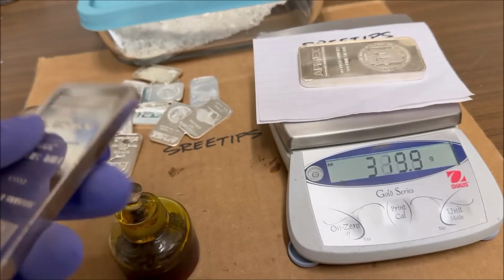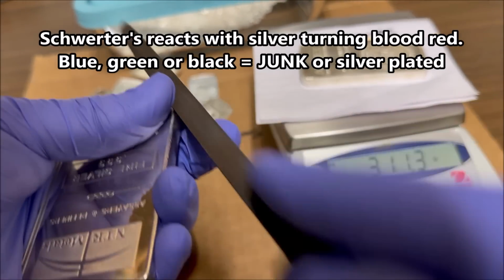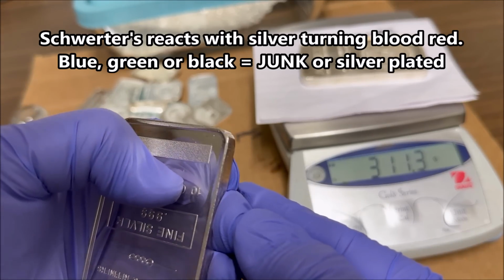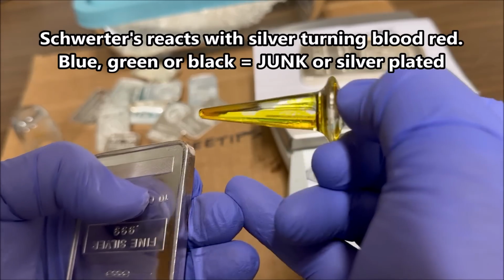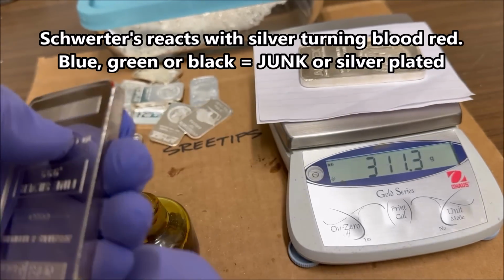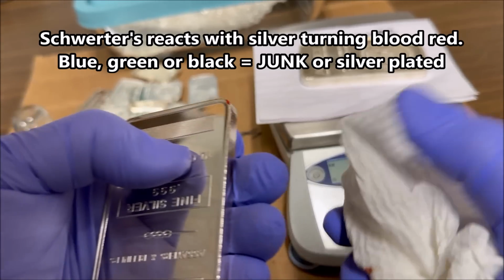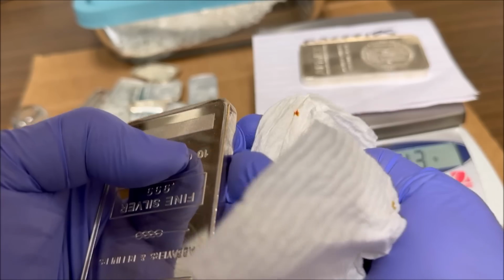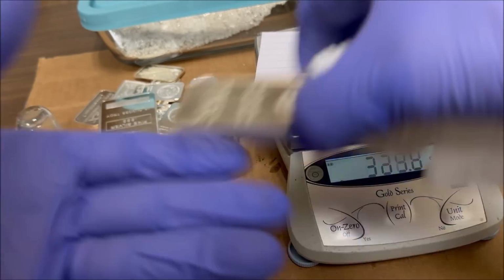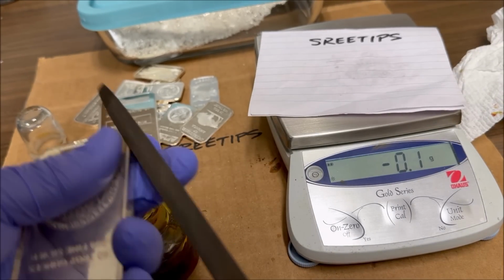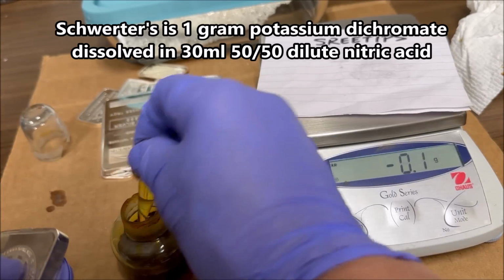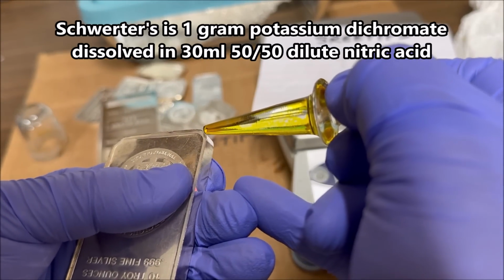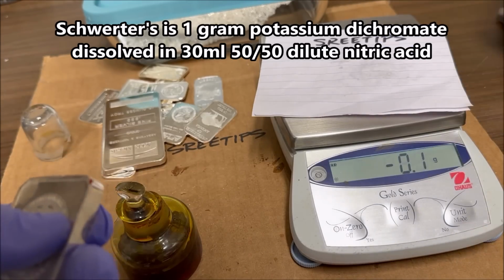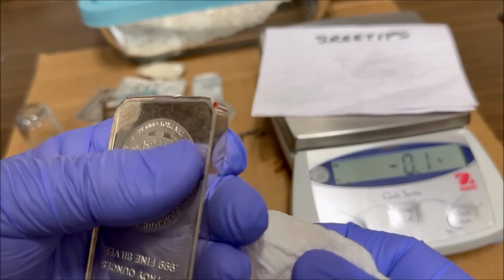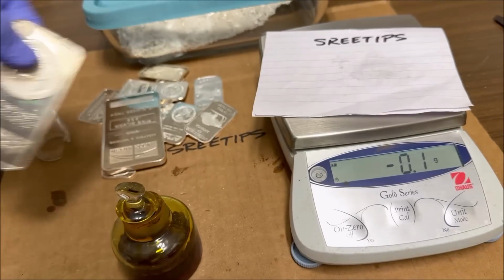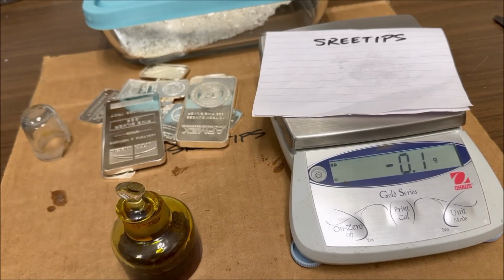What I'm using here is called Schwerter's solution. I file into the corner of the metal and then apply a drop of this, and it turns blood red, and that tells me that this is pure silver. Schwerter's solution is potassium dichromate, about 1 gram of it dissolved in about 30 milliliters of 50-50 dilute nitric acid. Alright, I've tested all this silver and it's all authentic silver.